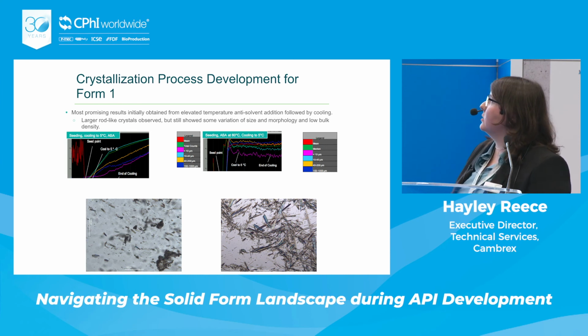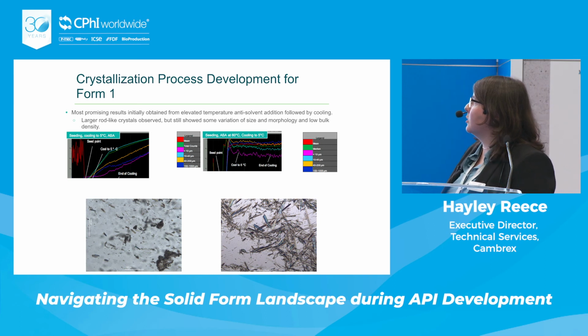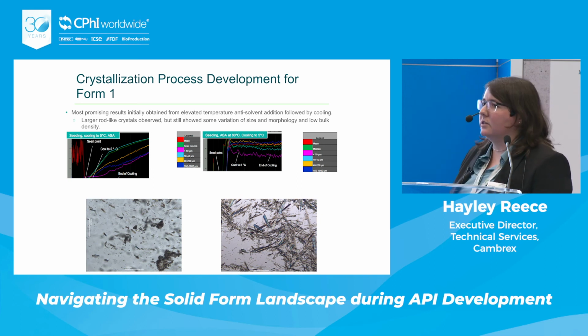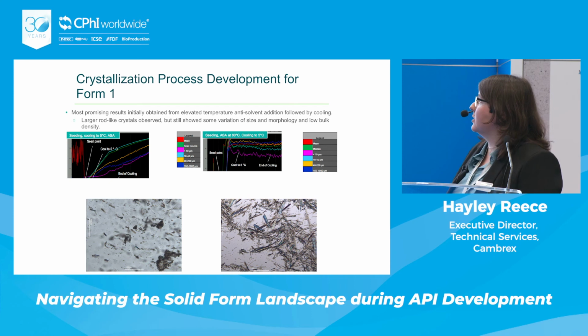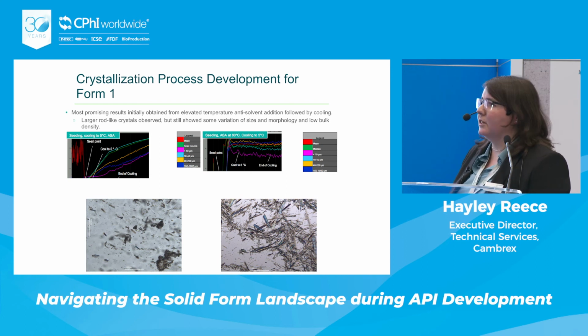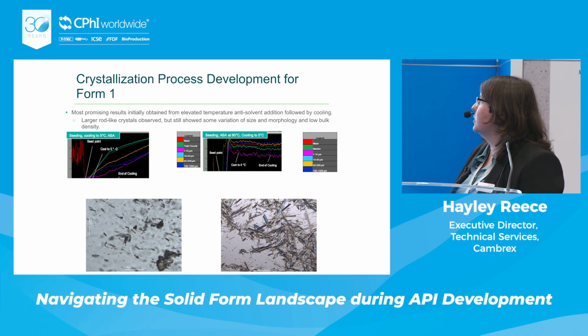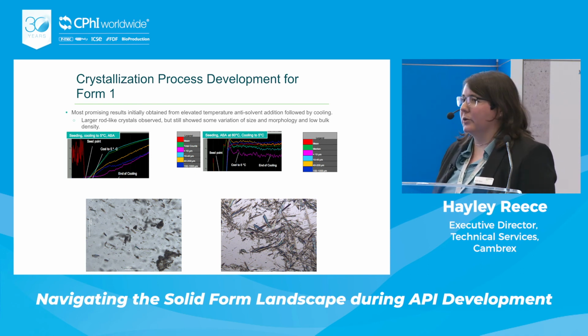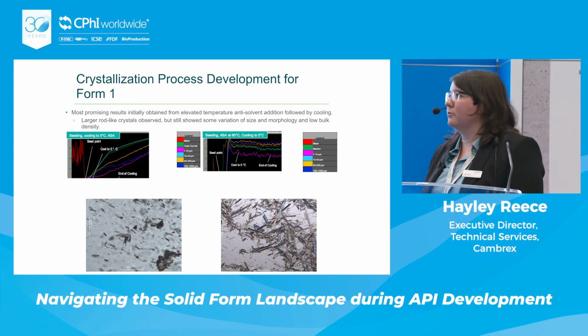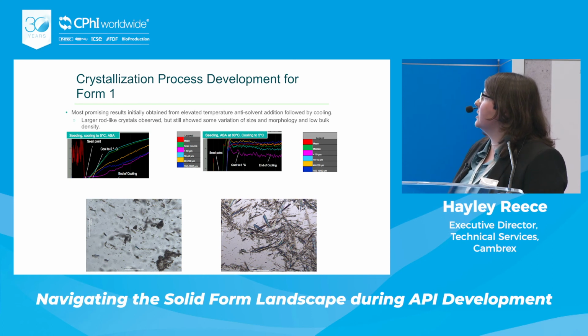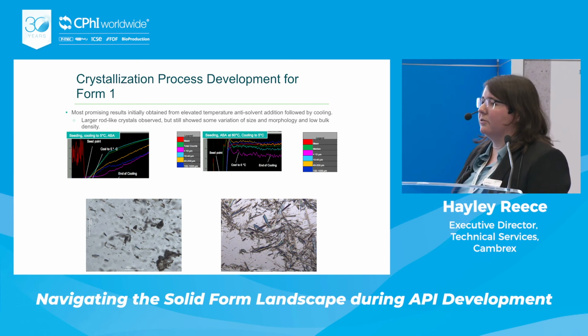So what we went on to do then is a second process where we added anti-solvent at 60 degrees, so slowly added ethanol at 60 degrees before cooling down to 5 degrees. And what we see here is a much steeper curve in the Blaze Metrics data. This essentially means that the material is crashing out of solution. It's coming out very quickly during the ethanol addition, and it's definitely not controlled.